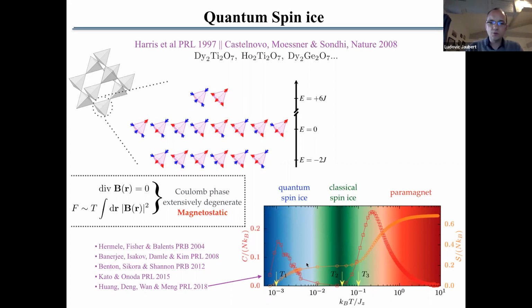And then with quantum Monte Carlo, you can go to even lower temperatures, see a second bump of specific heat, and see this entropy disappearing and going to 0. And that's where you enter the quantum spin ice regime, which is not degenerate anymore, where you can see it as a kind of quantum superposition of all of the classical states, in some hand waving.